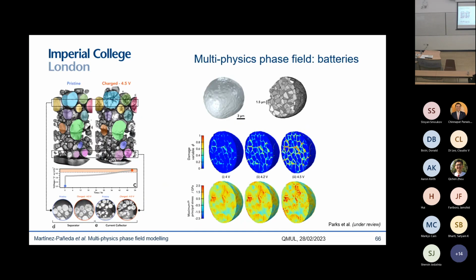And we have also taken this one step further and looked into the microstructure. And you can see here again, exploiting these amazing imaging capabilities that our colleagues at UCL have, we can capture very nicely, in this case, we're modeling intergranular cracks in the particles, as you can see.